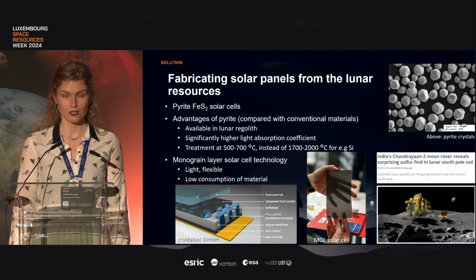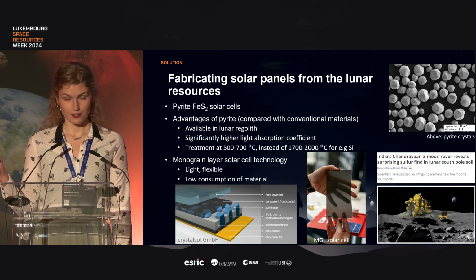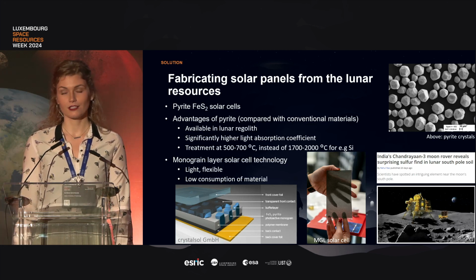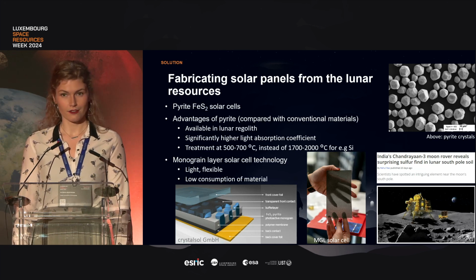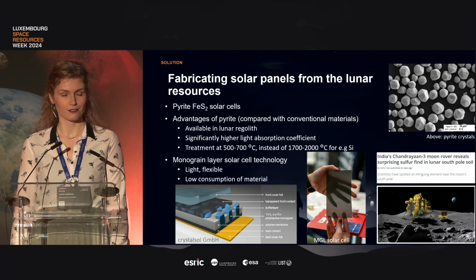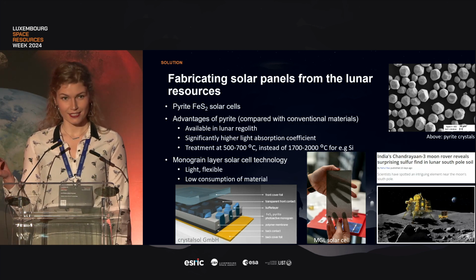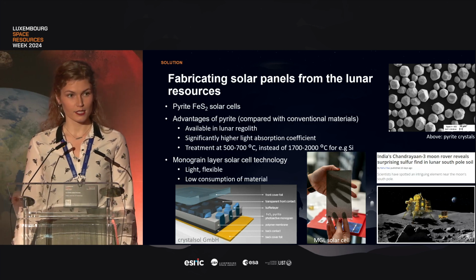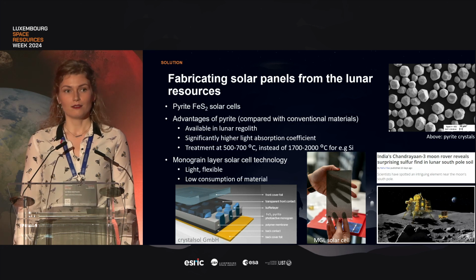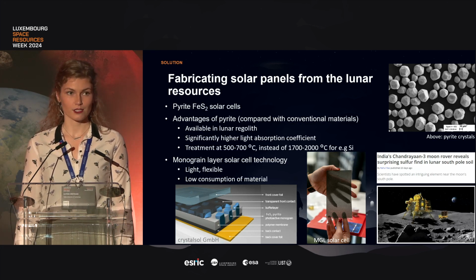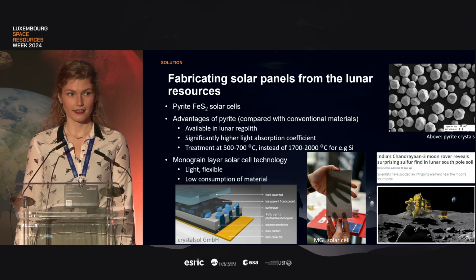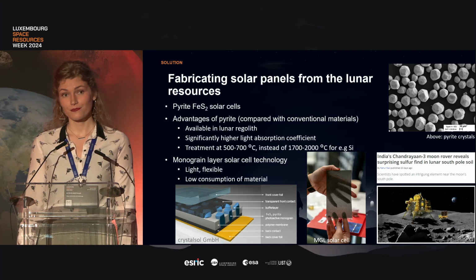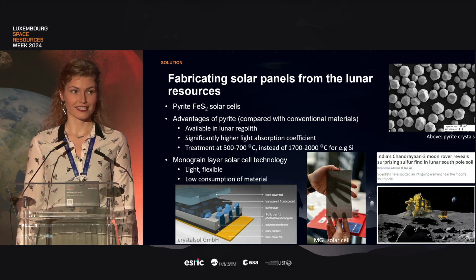And we focus on using pyrite, or iron disulfide, instead of silicon or other conventional materials as the photo-absorbing layer of the solar cells for many reasons. Well, first, pyrite or its elements are available in the lunar regolith. The recent Indian rover discovered sulfur in the lunar soil, thus confirming the predictions. Second, pyrite has a significantly higher light absorption coefficient compared to other conventional solar materials. That way we can use much thinner layers of material in the solar cells. And third, pyrite can be treated at 500 to 700 degrees instead of 1700.